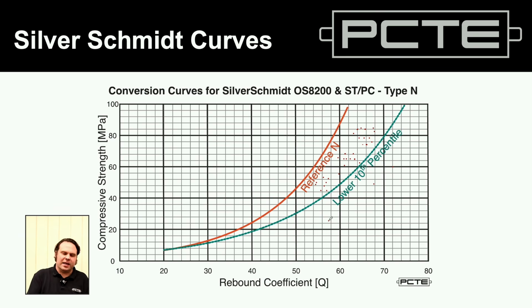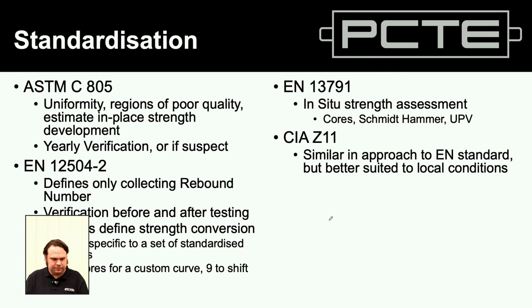The traditional reference N is different in that it is built with younger, fresher concrete, so newly cast, and also without that inherent conservatism to it. So no manufacturer curve is fantastic, but the lower 10 percentile is at least a little bit on the conservative side. Both of these are cube curves, so you do need to use inside your Silver-Schmidt Live or PC/ST model a correction factor to convert cube sample to cylinder sample. I'll show you that when I show setting it up.